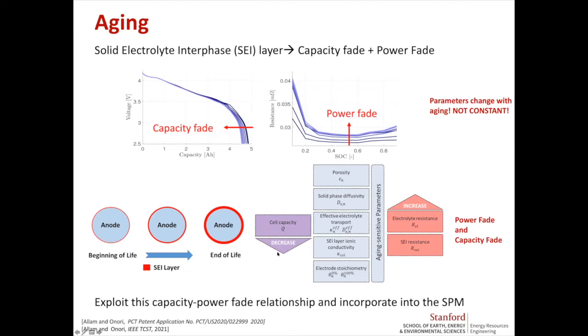But that's not the only thing that happens. What we incorporate in our model is also an update of electrochemical parameters like porosity. Porosity decreases, which leads to power fade. The solid phase diffusivity in the anode also decreases. Transport parameters in the electrolyte also undergo a decreasing trend, so ion conductivity and diffusivity in the electrolyte. At the same time, the ion conductivity in the SEI decreases as the lithium has to go through the SEI layers. And the electrode stoichiometry values will also undergo some changes. All of those changes in the electrochemical parameters lead to an increase of electrolyte resistance and also an increase of SEI layer resistance, which leads to power fade as well.